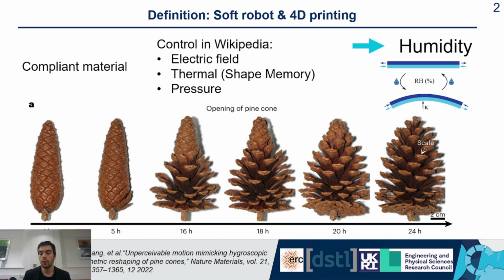And these different holes create different amounts of expansion when in contact with humidity. So one of the layers basically wants to expand, the other doesn't want to expand that much. And so you create stresses at the interface of the two layers when humidity changes, and therefore bending. And that's how the pine cone closes and opens. That's one of the soft robots available in nature.